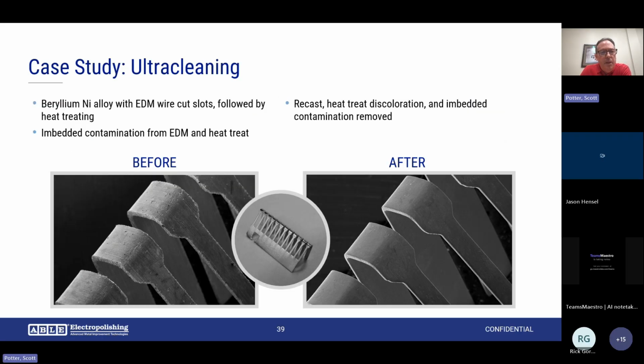There's a case study of beryllium nickel alloy. You can see how the slots were EDM'd, and then they were heat treated afterwards. So the electropolishing is very effective in removing the embedded contamination, and also removing the recast. It's a big thing for a lot of our customers. They're concerned about that remolten layer that you get on the surface, that recast layer that you get with EDM. It's a false surface on there, and it's prone to failure. So a lot of people use the electropolishing to remove that recast layer and to remove any embedded contamination as well.